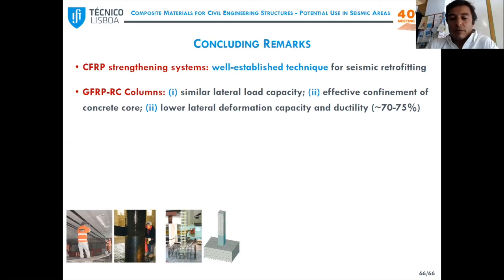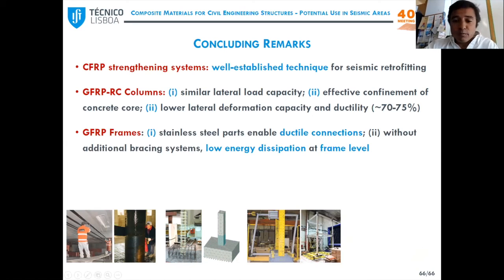Compared to steel columns, they were able to present similar lateral load capacity with an effective confinement of the concrete core. However, one needs to take into account that lateral deformation capacity and ductility are lower than with steel conventional reinforcement. For FRP frames, we found out that stainless steel parts appropriately combined with FRP enable relatively ductile connections. However, when we move to the structural scale without additional bracing systems, the energy dissipation is quite low.